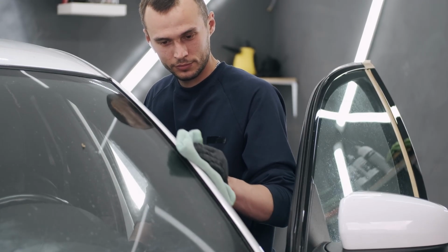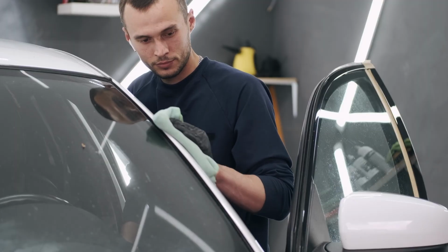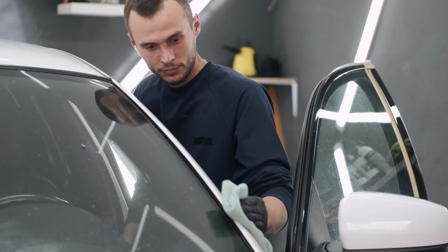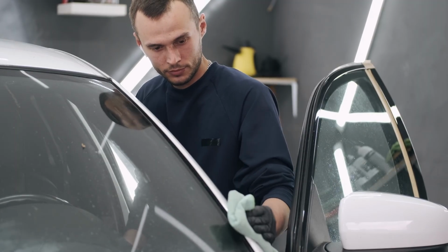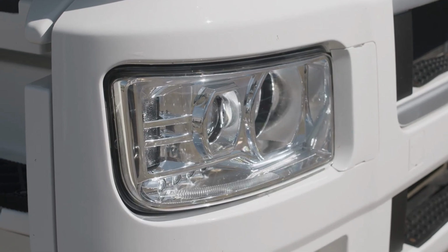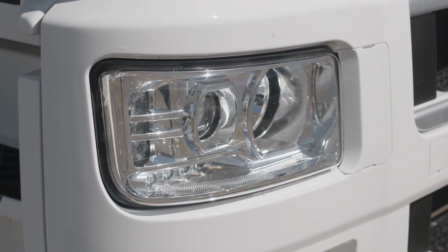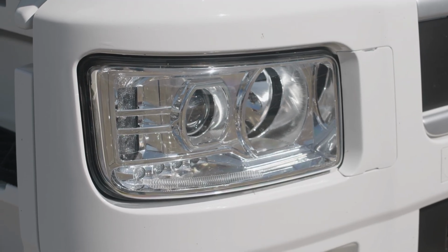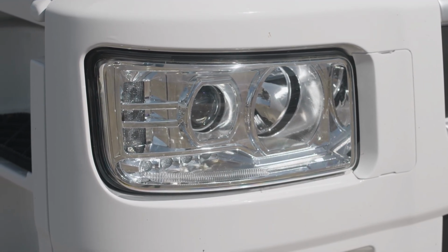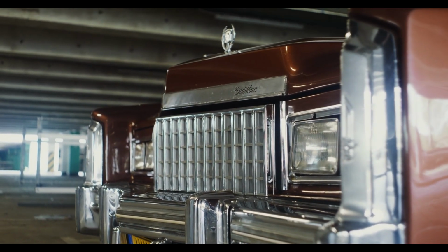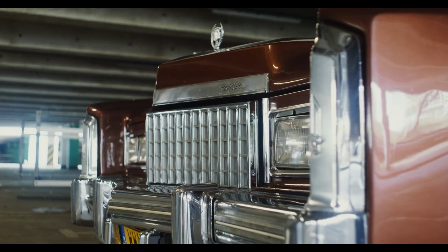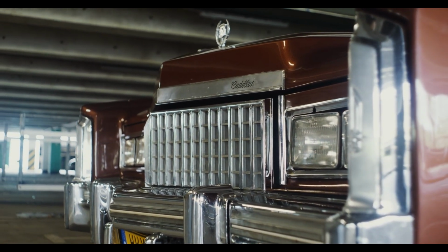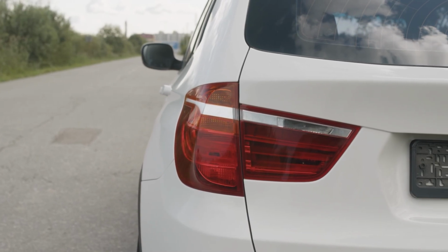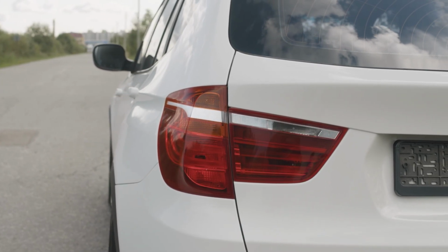Number 3. Sealing of joints with automotive-grade silicone. If during your diagnosis you detected that water enters, not only condensation but visible drops, number 3 is your solution. Often, the original glue, butyl, that joins the transparent glass with the black housing dries out and cracks. Do not try to seal it with bathroom silicone. The acetic acid of the domestic silicone will corrode the internal reflectors of the headlight in weeks. You must use neutral silicone of automotive grade or, better still, specific butyl cord for headlights.